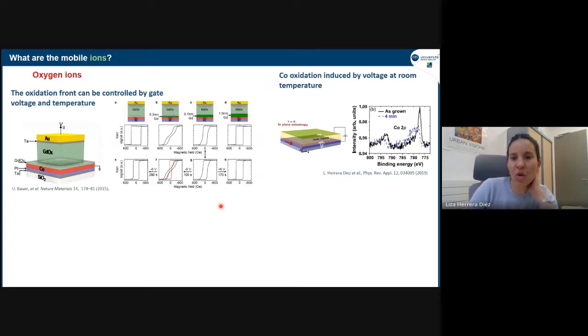This is something we could show as well in one of our systems. So we use platinum cobalt, here in the ionic liquid geometry. And we could really see by XPS that the metallic peak of the cobalt would decrease in intensity, and also give rise to another peak at higher binding energies, which is compatible with oxidation. So the cobalt is really getting oxidized. This is something that is very important and is different from the charge accumulation effects. Here, the magnetic films are really being oxidized. There's a chemical change that happens when we do ionics.